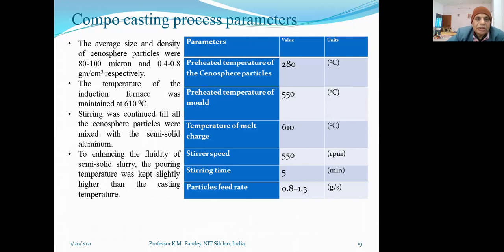So how this is done: the average size and density of cenosphere particles were 80 to 100 micron and 0.4 to 0.8 gram per centimeter cube respectively. The temperature of the induction furnace was maintained at 610 degrees centigrade. Stirring was continued till all the cenosphere particles were mixed with the semi-solid aluminum. And then to enhance the fluidity of the semi-solid slurry, the pouring temperature was kept slightly higher than the casting temperature.